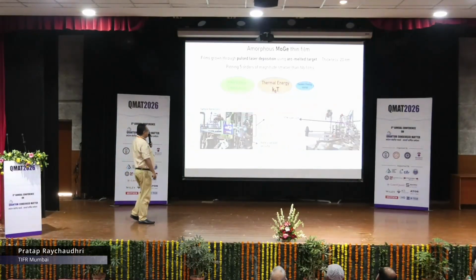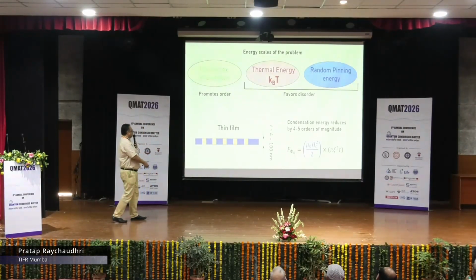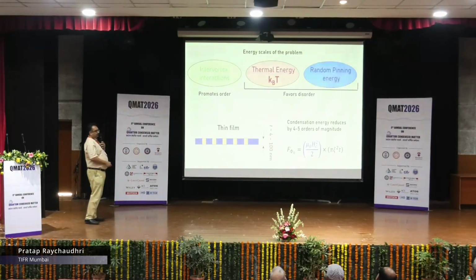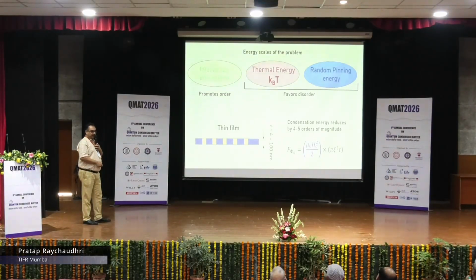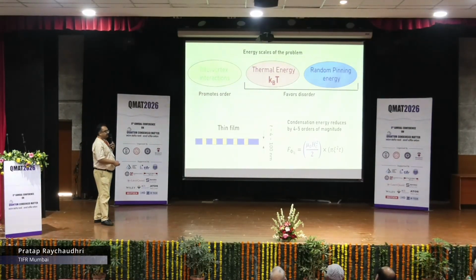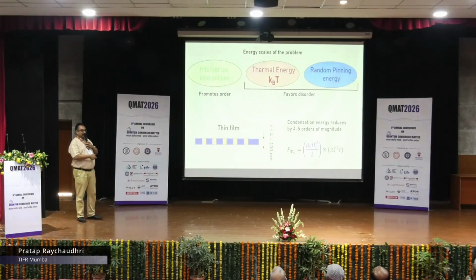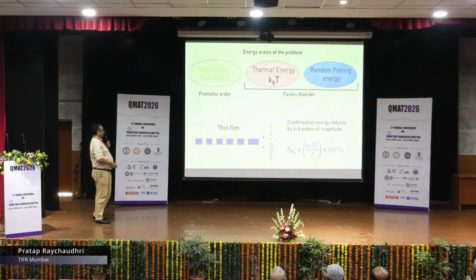On the other hand, this also tells you that if I reduce now the thickness of the superconductor to nanometers, I will reduce this condensation energy by 4 or 5 orders of magnitude, and now I have a hope that thermal fluctuation will start playing a significant role.